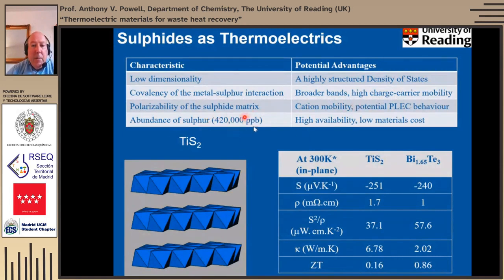Sulfur is also incredibly abundant, so that point I made earlier about the abundance of the materials becomes really quite important. And we were really struck by the fact that if you take TiS2, these are some data from the literature, you find that electrically TiS2 is actually quite good. It's performing in quite a comparable way to bismuth telluride. What kills it is the thermal conductivity. So at 300 K, ZT drops from about 0.86 down by a factor of almost 5, and that's predominantly because of the thermal conductivity.